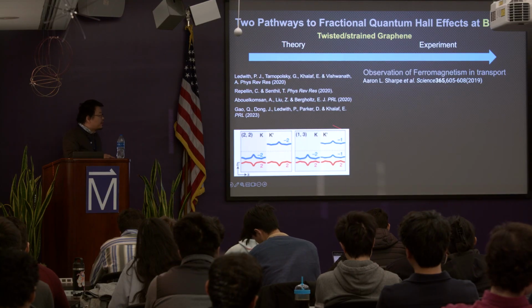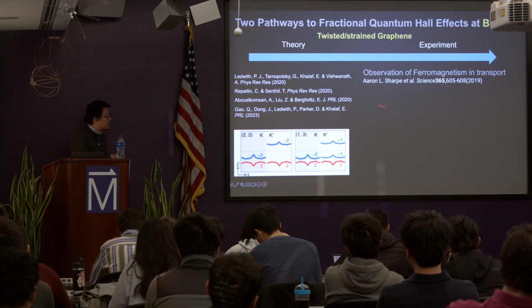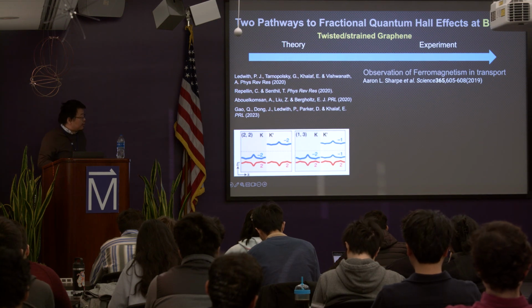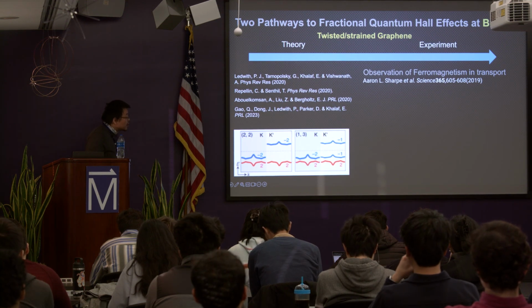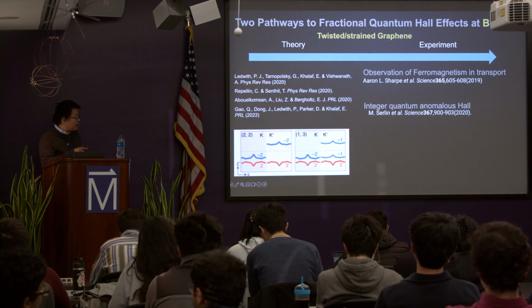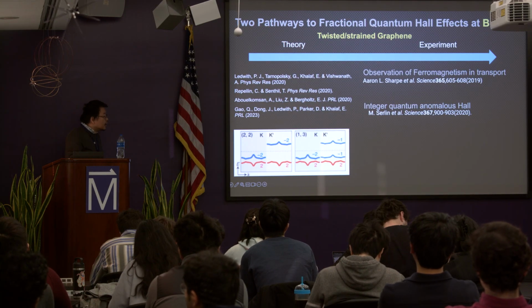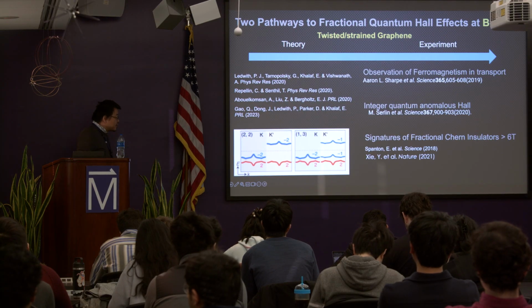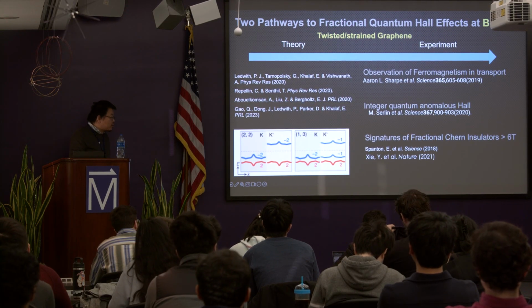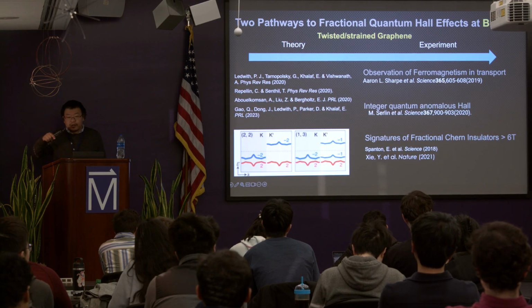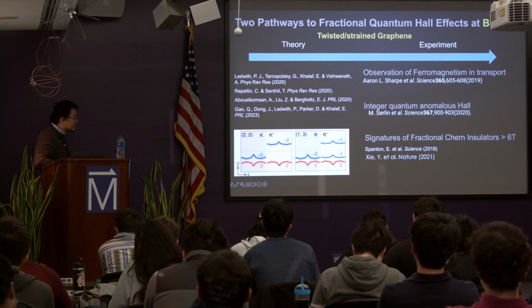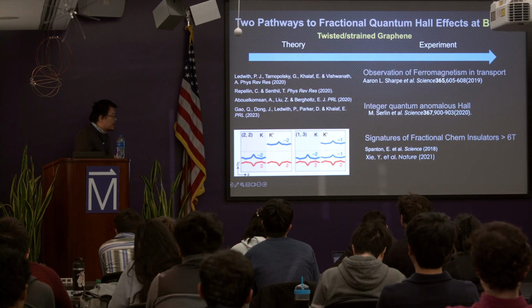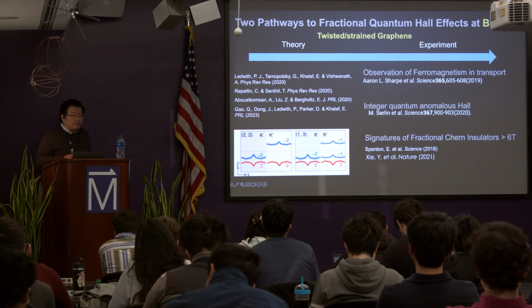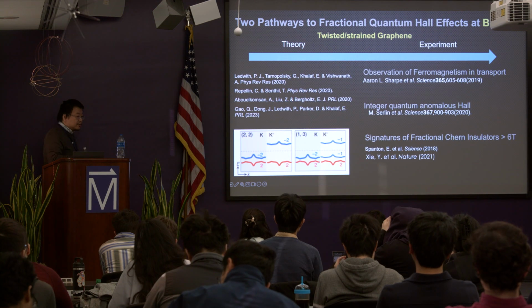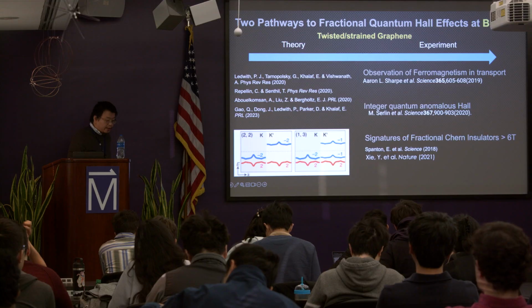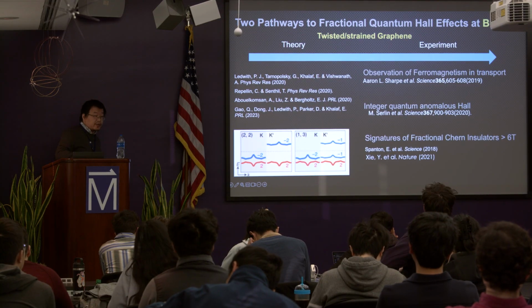First, you can see that ferromagnetism has been observed in TBG, like in David Goldhaber-Gordon's group. And following that, the integer quantum anomalous Hall effect has been discovered by Andrea Young. And so far, the best try is actually from Amir Yacoby's group. They use a scanning single electron transistor that can locally measure the compressibility, and they saw a signature of the fractional Chern insulator around 6 Tesla. But so far that's the best try.